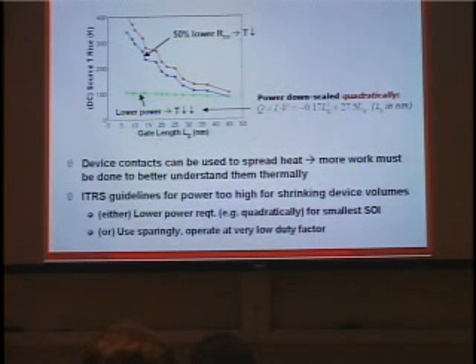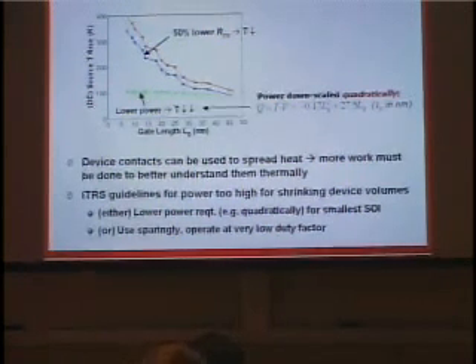Again, I'm plotting the source temperature rise in DC as a function of gate length along the ITRS guidelines. And what I've done here is, between the red and the blue line, I've reduced the contact thermal resistance. This is the thermal resistance between the via, the silicide, and the silicon. So in a way, what one could do with these contacts is use them to spread heat, just as one could increase the source and the drain to give more volume for heat to spread into. The same thing could be done with the contacts, at least that's what this model seems to indicate. Of course, more work has to be done to understand the contacts better thermally.